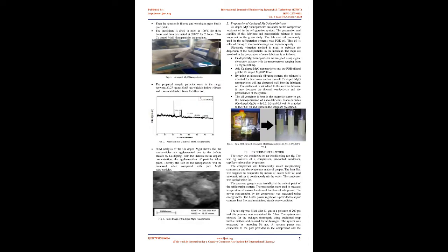2. Preparation of nano-lubricant. MgO is an important material that has wide range of applications in catalysis, toxic waste remediation, paints, superconducting products, and antibacterial activities. The MgO compound has boiling point about 3600 degrees C and melting point of 2852 degrees C. These oxide materials can be synthesized by different methods like solution combustion, chemical precipitation, sol-gel, hydrothermal, solvothermal, microwave-assisted sol-gel, and green synthesis etc. Among these methods, co-precipitation method is one of the best methods to synthesize nanoparticles without agglomeration in the production.